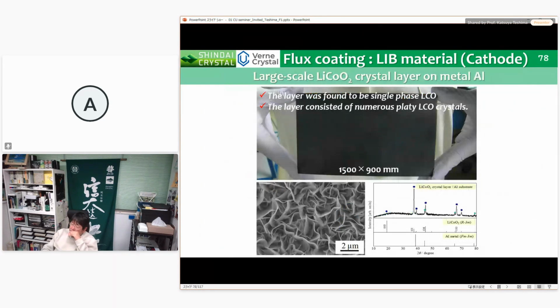This is a large-scale LCO crystal layer on an aluminum substrate. The layer was found to be single-phase LCO. As you can see, the layer consisted of numerous platy LCO crystals. Now I'm checking these LIB performances.